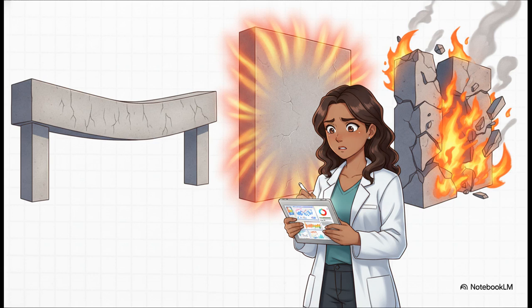Well, the research team is going to watch like hawks for a few specific failure criteria defined by the standard, pushing these specimens for up to 2 agonizing hours. First, failure happens if the beam bends or deflects by 10 millimeters. It also fails if the temperature on the unexposed side of the beam rises 140 degrees Celsius above room temperature. That's a huge one, because in a real building, if the back of a wall gets that hot, it can instantly ignite whatever is in the next room. And of course, total structural collapse or direct flame penetration means the test is immediately over.